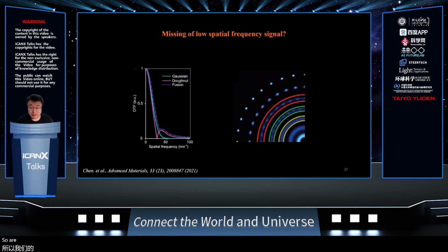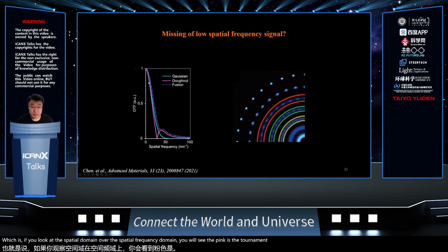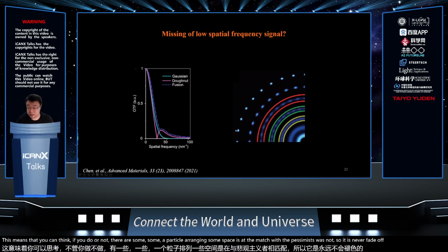But there's some challenge. Previously I only mentioned that we can use the donut to do the imaging, but the donut has some limitation. If you look at the spatial frequency domain, the pink is the donut beam and the OTF. This OTF means all the frequency signal inside your image. If you use the donut beam, there's some missing frequency over here. It means that if there are particles arranged in some spacing that actually matches the donut pattern, they never show up. So this happens here.